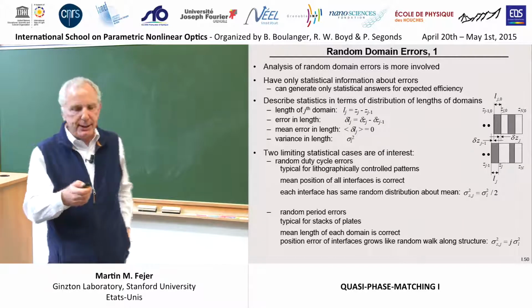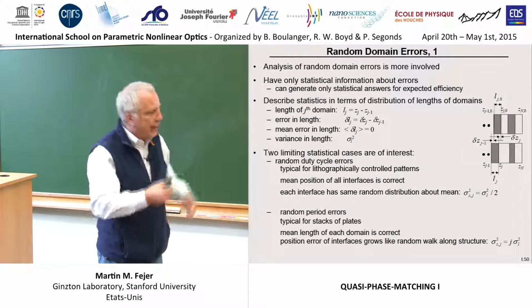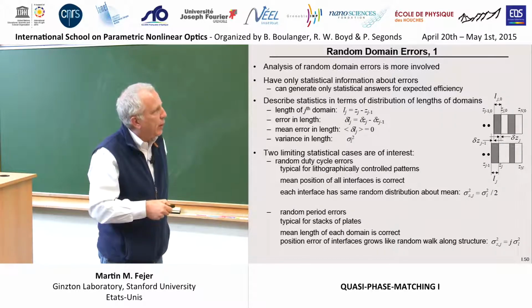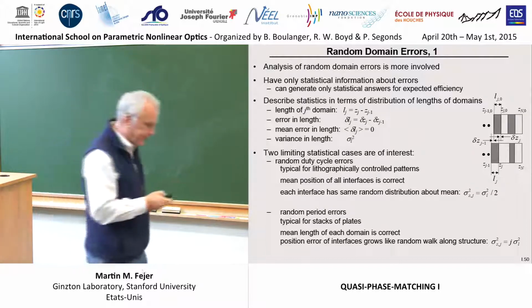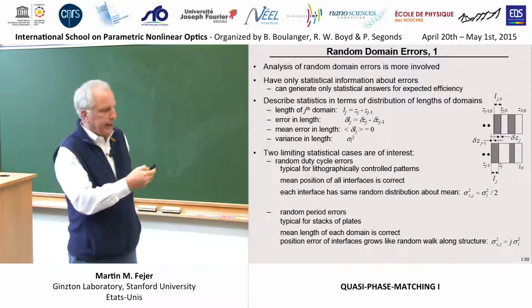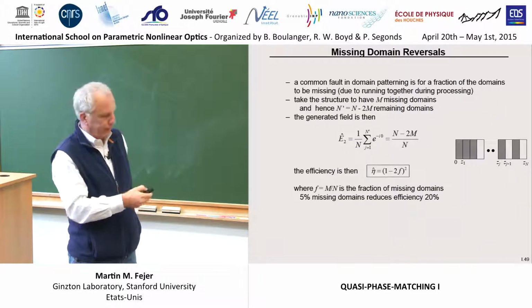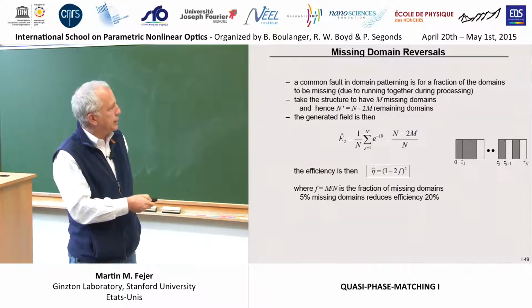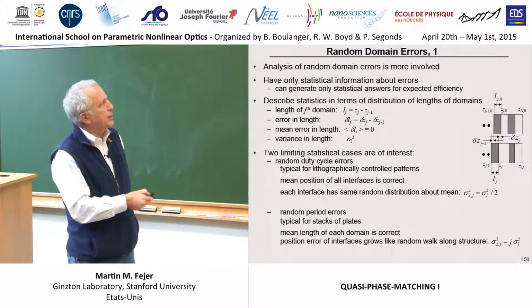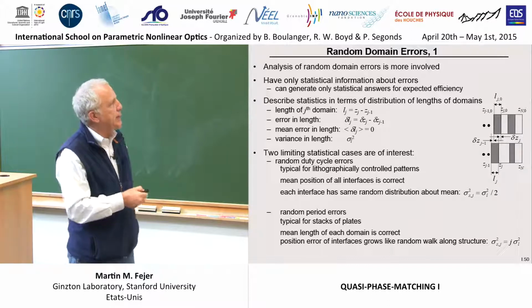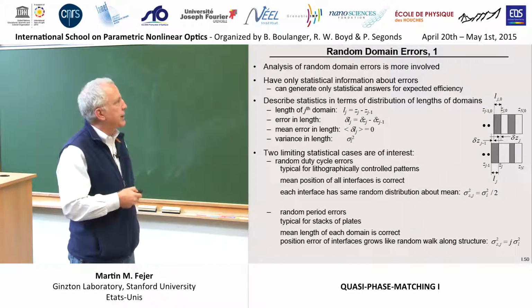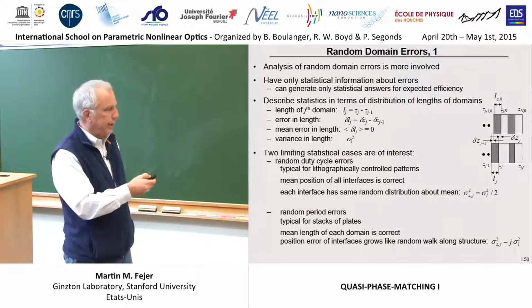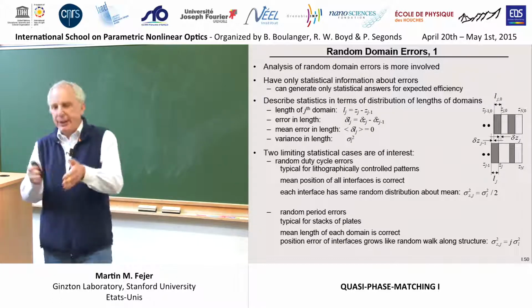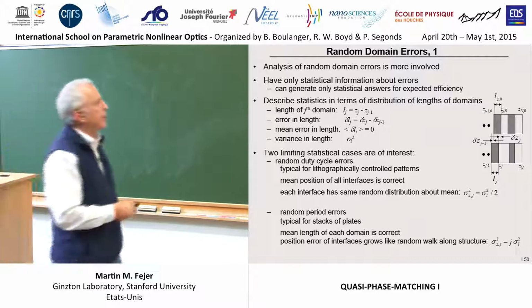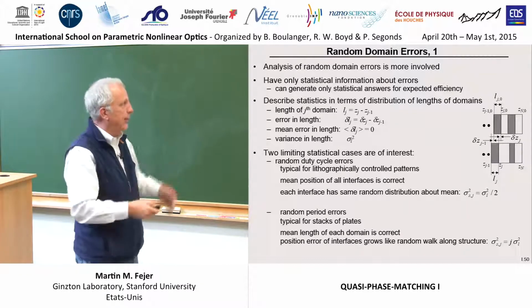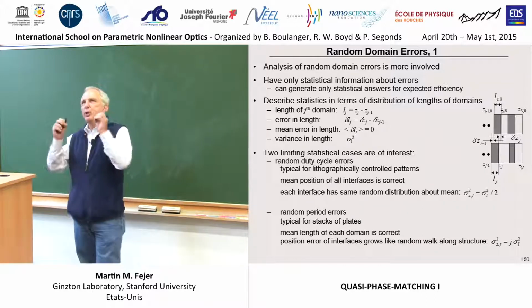More common than missing domains, at least in the modern era, are random errors in the position. That is, you have all the domains you're supposed to have, but the edges aren't quite where they belong. So if we define the error in the length of one of these domains as just the difference in the position here to here, then there will be some distribution of domain thicknesses. Typically, the expected value of these is 0. They're randomly too long or too short. But they'll have some variance in the length of these domains associated with these errors, and that we'll just call sigma sub L.